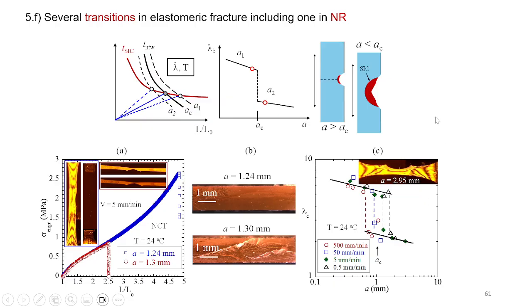There were a couple of fascinating transitions, one of which deals with natural rubber. So natural rubber is known for a long, long time: when you change the cut size just by a few percent, it will change the strength, or your resistance to crack propagation in the language of energy release rate, by a lot. So this is data, for several different rates that you did this. So this is a pre-cut, and then you basically imagine using a cut size just here or just here. It sharply becomes stronger when the cut size is only a few percent smaller. And this is sharp. People don't ask the question why it's so sharp.